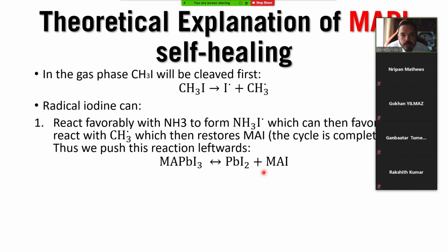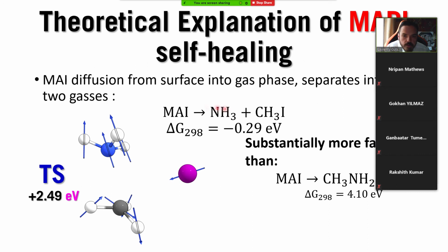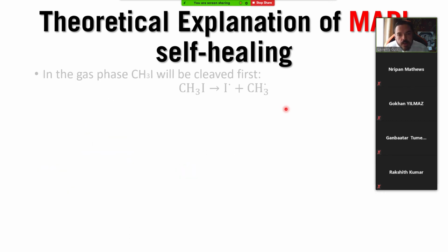So what happens? Well, first in the gas phase, we've gone through this reaction, right? We've gotten methyl iodide. It is cleaved. So as we know in mass spec, the heaviest atom is cleaved first. The weakest bond is cleaved first. So the weakest bond is of course the iodine methyl bond. So that's cleaved first, and we get an iodine radical.